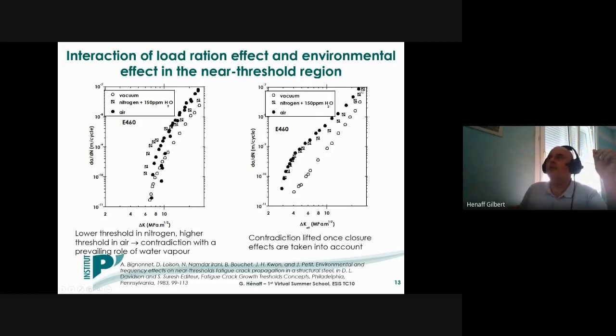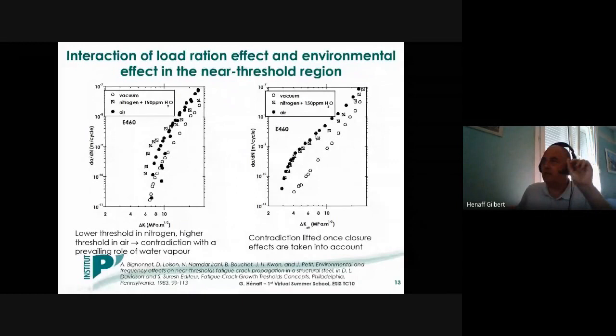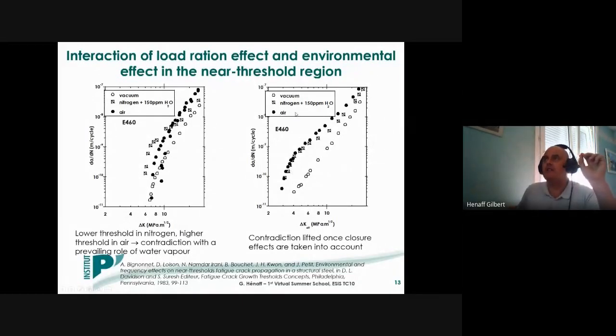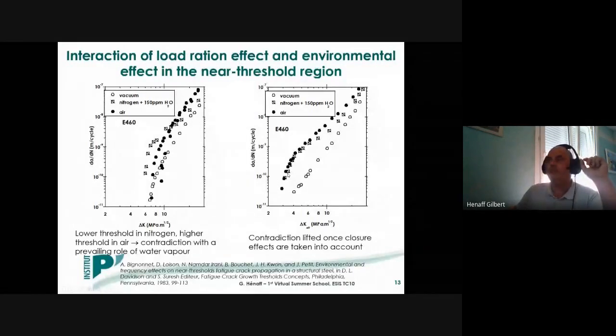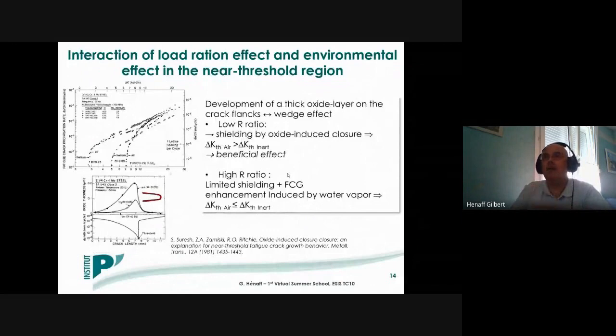Here we have an intermediate behavior represented by this mixture of nitrogen and traces of water vapor, and the highest crack growth rates obtained in air. However, we can notice that for this atmosphere with only traces of water vapor, we have a threshold value which is comparable to the one observed in air. And this was also studied, for instance, by Suresh and Ritchie in the United States. These are very famous results. This type of observation is similar to the one that I have shown before.